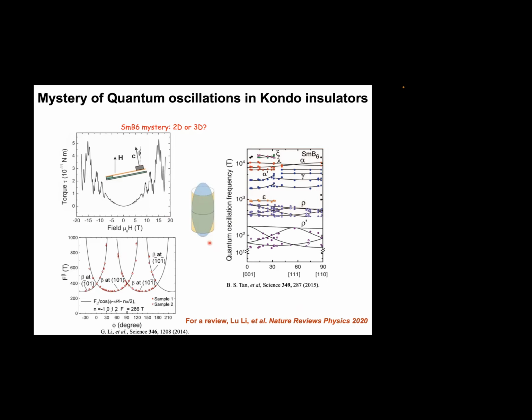That's a difference there. So to us, that raises the interesting question of whether it's indeed 2D or 3D. In particular, their samples also showed oscillations that are way bigger than what we observed here. Here it comes into the 10 kilotesla range, where the oscillation frequency is in a range comparable to copper, gold, or silver, all these noble metals. That's what our sample did not show, and unfortunately, we were not able to confirm that. But if that's indeed the case, there's just no debate that that's definitely a bulk phenomenon. Okay, but that's an important question. As you can see, my data supports this type of Fermi surface, but that can still be bulk or surface.